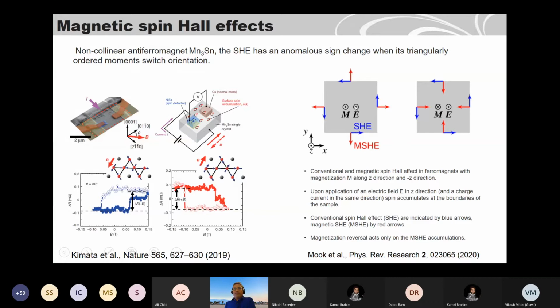So when you apply an electric field in the material, for the spin Hall effect, these blue lines show the spins accumulated on the surface. When you change the magnetization orientation, with the electric field the same, from in plane to perpendicular, or from one side of the material to the other, what should change? The spin Hall effect direction should not change for the conventional spin Hall effect. But if it is magnetic, that should change. What you see here is the magnetic field pointing into the screen, so the spins coming out from the magnetic spin Hall effect are pointing outwards. But when you change the direction of the magnetic field, the spins are pointing inwards.